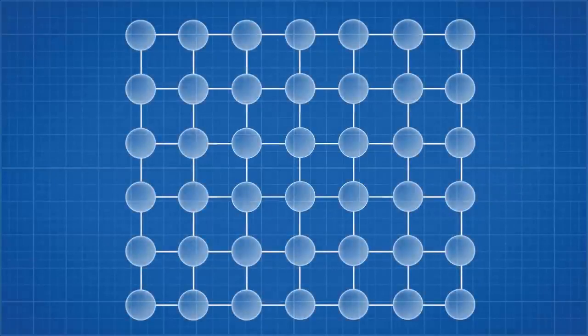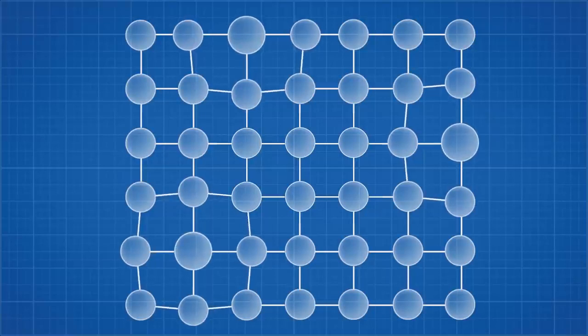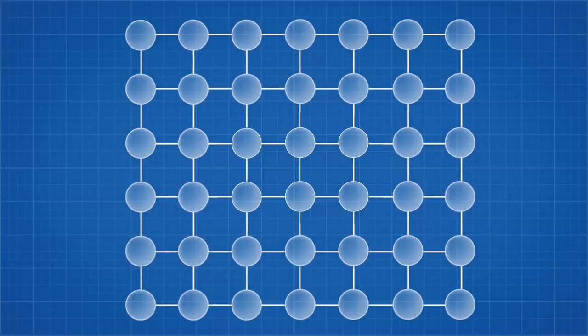What happens when we swap some of these aluminium atoms for copper? Copper atoms are slightly larger than aluminium, and they create internal strain when fitting into the aluminium crystal lattice. When the alloy was heated, the copper spread evenly through the material, and the quenching process trapped the copper in these locations. In these positions, the copper atoms do not provide much strength, but over time, they will begin to